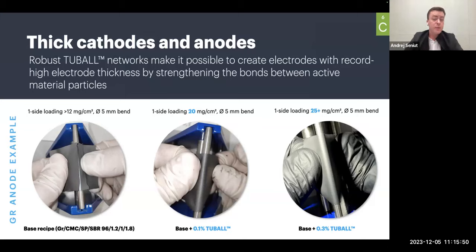In this case, this is a comparison of graphite anode, standard 12 milligram per square centimeter one-side loading, 96% graphite, 1.2% CMC, 1% carbon black, 1.8% SBR. And you can see that by testing this anode by using 5mm bend, there is a crack in the anode. But if you add only 0.1% of TUBALL on top, you can increase the loading of your electrode up to 20 milligram per square centimeter. And by doing the same test, you do not see cracks. So the electrode is more flexible, it bends much better. If you add more TUBALL, the result is even more pronounced. So plus 0.3 TUBALL on top, you can increase the loading higher than 25 milligram per square centimeter one side.